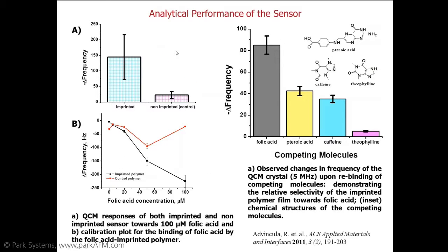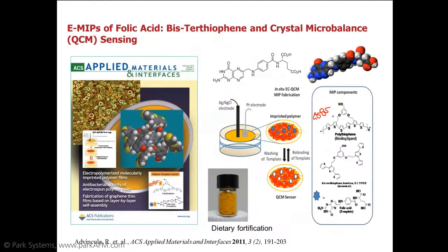We then try to demonstrate this and compare it with other analytes. So for example, first of all, the imprinted is superior to the non-imprinted. The frequency shift of the imprinted, meaning a higher signal-to-noise ratio, was observed with the imprinted versus the control. And then we tried to compare the performance of this sensor based on folic acid against pteroic acid, caffeine, and theophylline. So obviously the highest response was found with the originally templated molecule. Okay, and this was published back in 2011 in ACS Applied Materials, and in fact made the cover page for the journal as shown here.